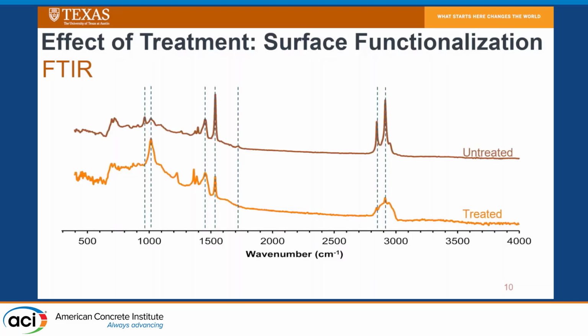We did FTIR analysis to get a better understanding about what was actually happening with this treatment process. And the orange line below shows the treated samples. This is after the 2-step treatment. And the, I guess, brown line above is the untreated samples. And I'm going to point out some key wavelengths here because they correspond to different functional groups to give you an understanding about what is happening with this treatment process from a chemical point of view.